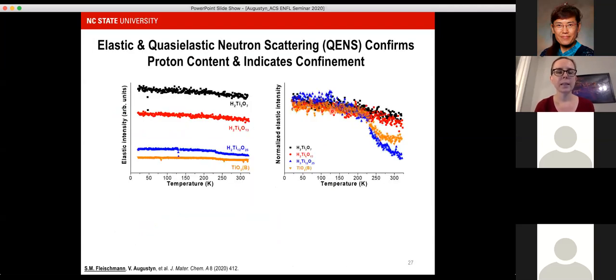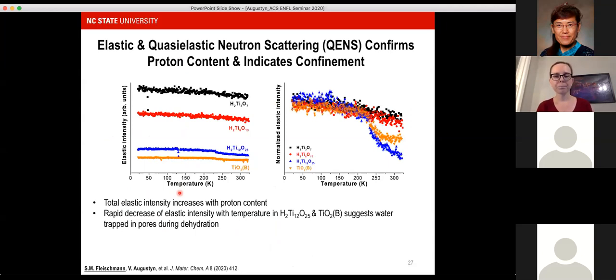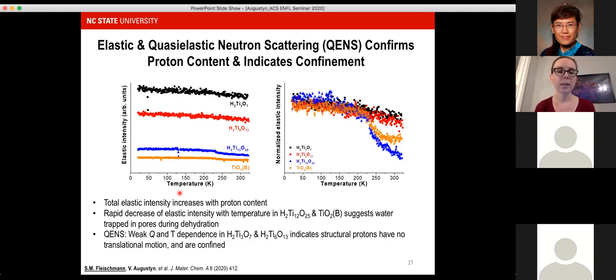Again, we did the elastic and quasi-elastic neutron scattering, which told us that those interlayer protons were present as we would expect. So the elastic intensity increased with proton content. We saw some interesting effects of the synthesis that suggested water was getting trapped in pores during the dehydration process. And then we also found that there was no translational motion of the interlayer protons that were present.